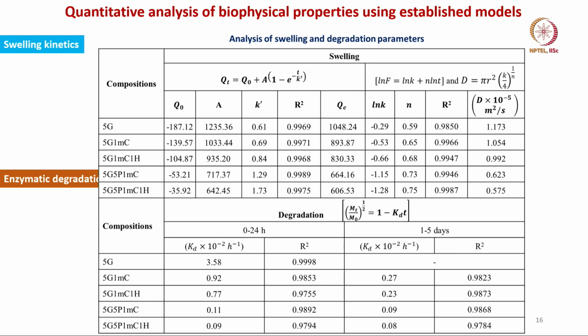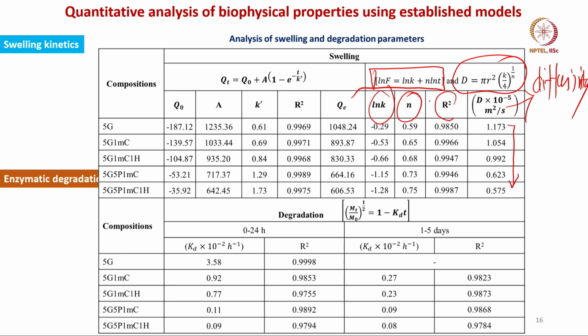You can see more values in terms of quantitative estimates of this n value, that is the swelling kinetics, and then also ln k, and then you get the diffusivity. So, diffusivity is nothing but pi r square k by 4 to the power 1 by n, and if you look at this diffusivity, it is also reduced by modifying the hydrogel composition. And this particular experimental data, when fitted with the equation ln F = ln k + n ln t, shows good statistical relevance, with the correlation coefficient close to 0.99.